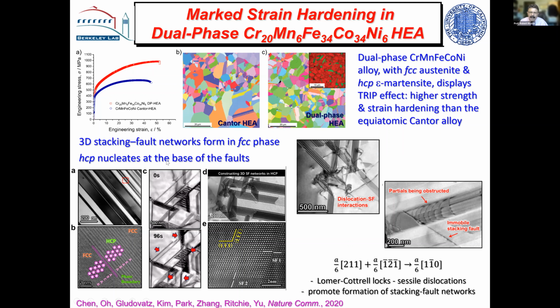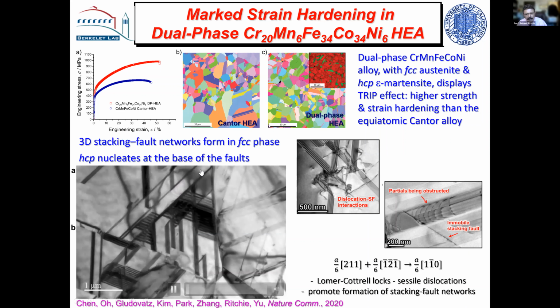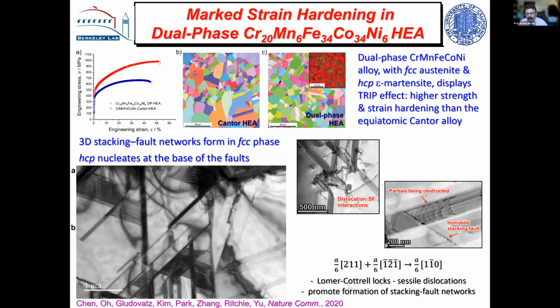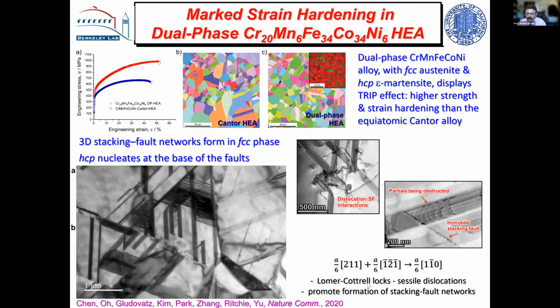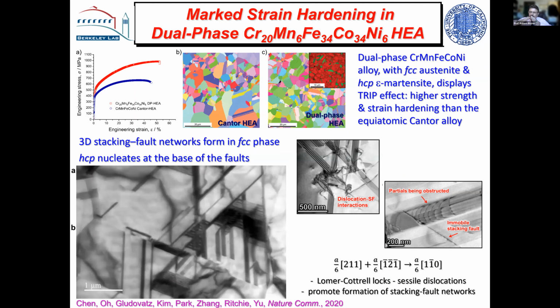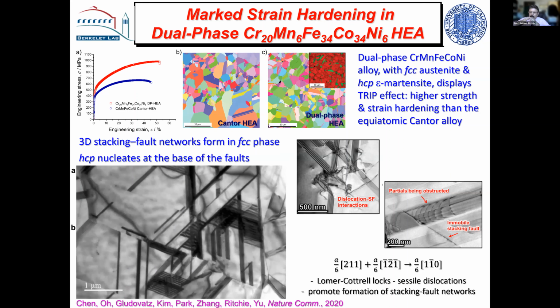And it's very interesting to see what you see. You see these stacking fault networks. And I can show you one here. These are these networks of stacking faults. And they are remarkable barriers to dislocation motion. One of the things that allow these to form is you see these so-called Lomer-Cottrell locks, which are sessile dislocations in these alloys. It's when you get two partials come on two planes, intersecting planes, and form then a sessile dislocation.